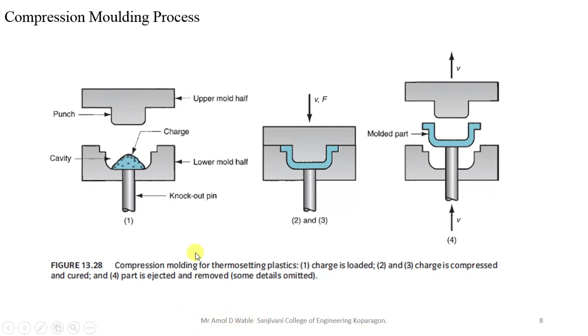So you can see that compression molding is mainly used for molding thermosetting material. In this molding method, the material is generally in powder or pre-formed shape and it is loaded directly into the hot die cavity. A measured amount of plastic powder or a viscous mixture of liquid resin and filler material is placed in the lower female cavity, which is continuously heated by either steam or electricity.